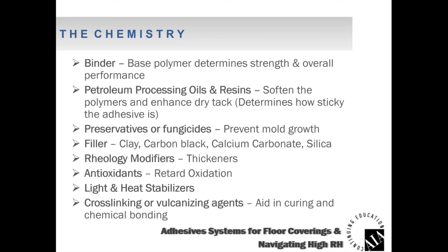There are also light and heat stabilizers in the adhesives, so that they're not affected by light. High heat can have a negative effect on the adhesive as well. So you've got those types of constituents in the formula. And then finally, you have cross-linking or vulcanizing agents that help in the curing and the chemical bonding of the adhesive.